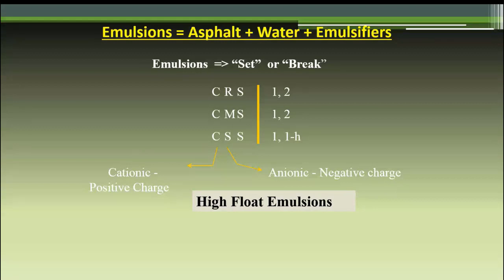I know the first chip seals we did in Wyoming with emulsions, though, we had a big problem because our chips were too dirty. So all of a sudden, snowplows are peeling that thing off like peanut butter off a slice of bread. And we came to find out, we got to use a different emulsion. And high floats were kind of designed to be a little more dust tolerant, but more and more states have moved to better specifications, better designs for chip seals. The amount of high floats have gone away, but there's still a use for them out there.